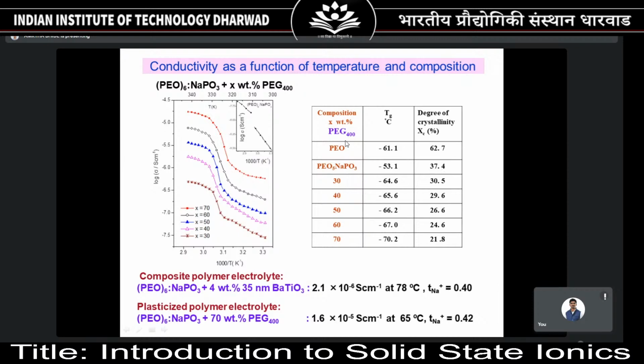And then we kept on adding this plasticizer, polyethylene glycol, a low molecular weight polymer, in different weight percents. The crystallinity has decreased, which proves the images that we have seen in the optical micrographs. Now look at this diagram, which shows temperature dependent conductivity as a function of different compositions, 30, 40, 50. Unlike composites, as we increased the content of polyethylene glycol, the conductivity also enhanced.